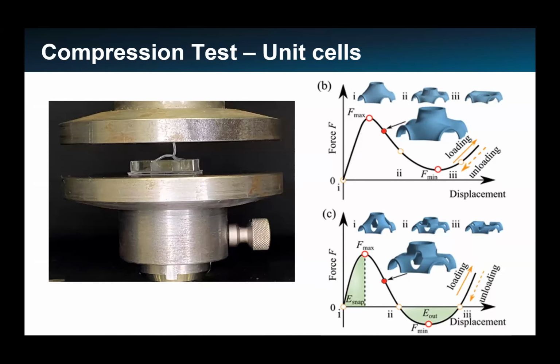These tests involve compressing a single unit cell of the lattice structure using a testing machine, while measuring the load and the deformation response. The goal of this compression test is to determine the compressive strength, the compressive modulus, and other mechanical properties of the unit cells that can be used to predict the behavior of the entire lattice structure.